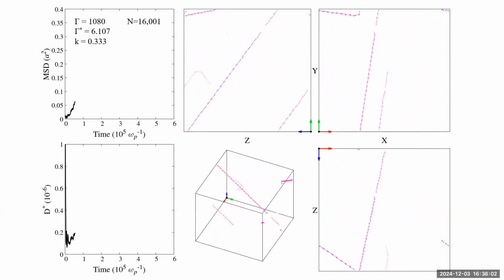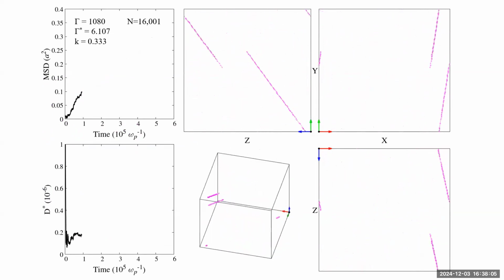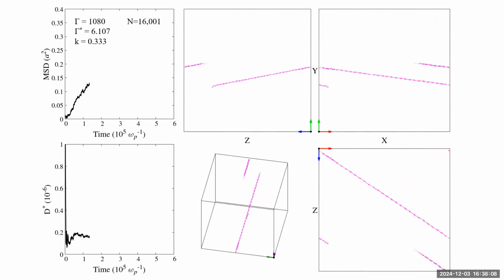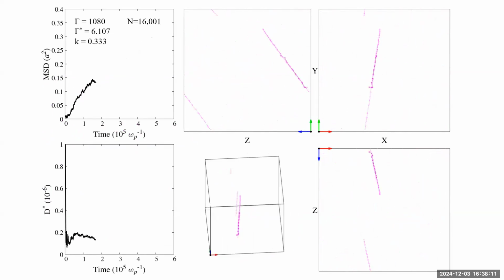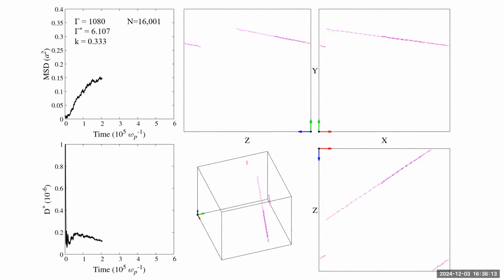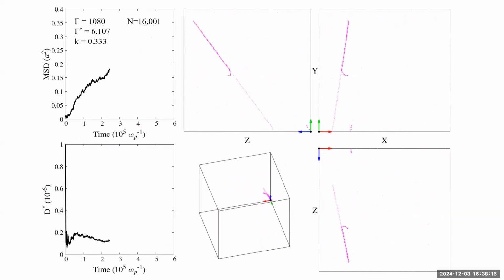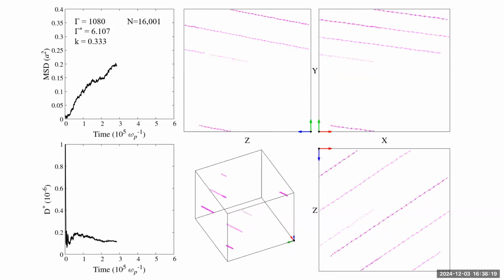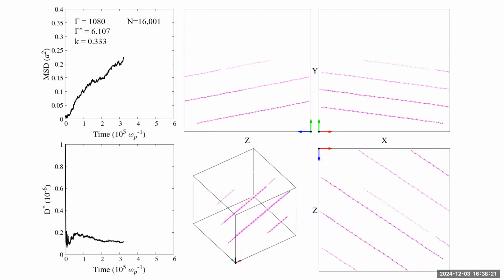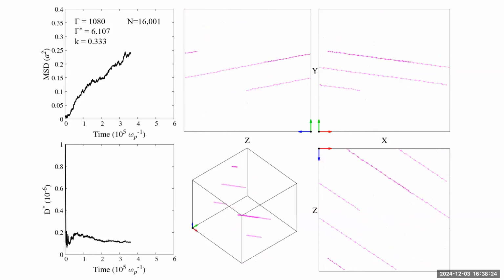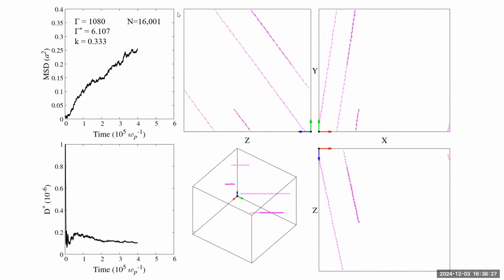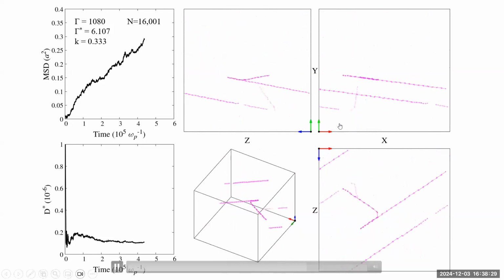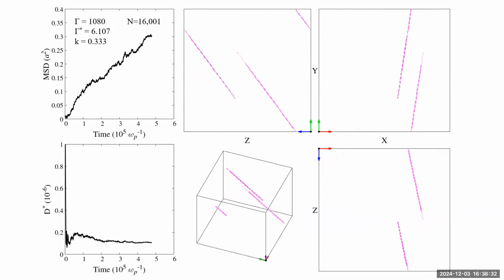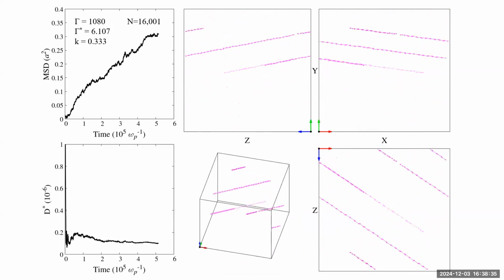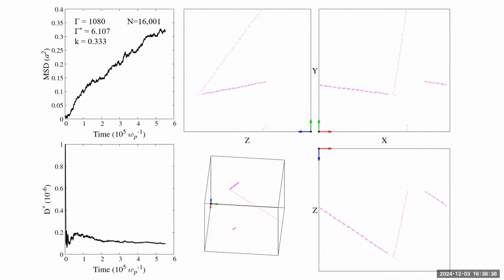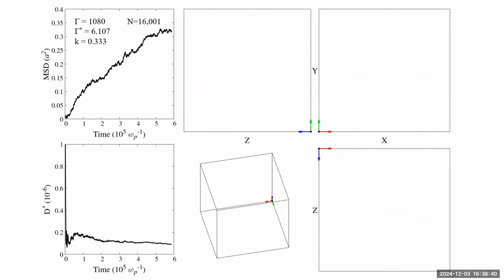The hops, these diffusive hops, are highly correlated. Those snakes that I was showing you a minute ago, once the defect had moved by a lattice spacing, it was basically rolling the dice to pick which of the neighboring lattice sites it was going to move to. But now, the crowdion, because it forms this sort of long quasi-particle, it is much more likely to move forward than it is for it to rotate and move onto a different diagonal or a different stack in the lattice. So again, you have this diffusion, you pick the average slope here, that tells you the diffusion coefficient, and you get a diffusion coefficient for the interstitial.